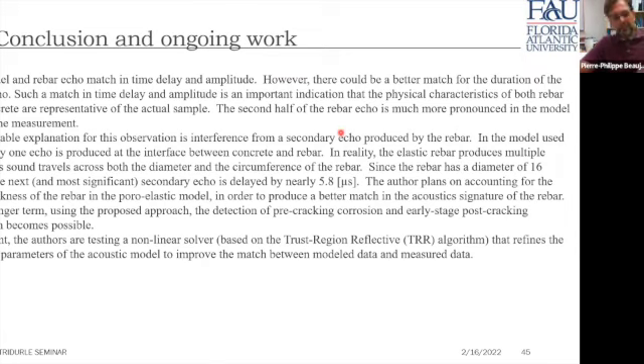Now, let's jump to the conclusion, given the little time we have left. In terms of conclusion and ongoing work, I mentioned first that there is some improvement needed in terms of matching what the model produces and what we measure, in particular when it comes to the secondary echo coming from the rebar. Now, I would like to mention, and that is going to be at the bottom of my conclusion right here, a really important one: as we speak, we are testing the nonlinear solver based on the trust region reflective algorithm to refine the physical parameters of the acoustic model in order to improve the match between the model data and the measured data.